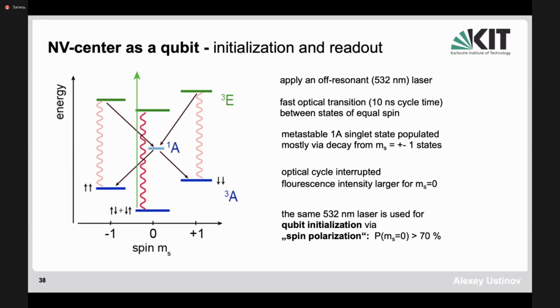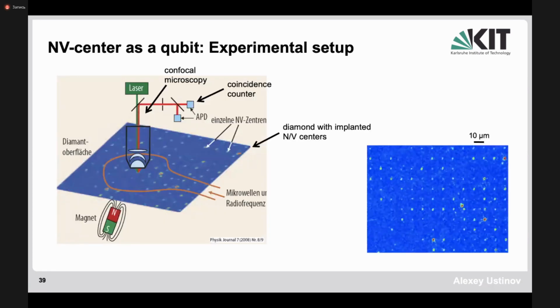Now, the qubit initialization can be done by spin polarization, basically by pumping this to high energy state and then corresponding relaxation. So you'll prepare some of the lower states here in a desired fashion. And then the technique of doing the measurements will be basically applying light pulses and microwave pulses to these spin states, to individual defects. Now, the question is, how would we observe these individual defects? And this is really a very beautiful part of this technology here.